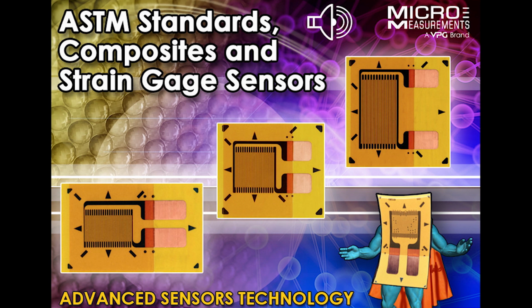It covers the whole area, and if you want to read more about it, I know Bob Watson had a presentation at Micromeasurement about it, where you'll see that if you use an actual shear pattern like an 062 UV, you will not get the whole spectrum of where the strain field is through that specimen. So unless you have a correction factor for these gauges versus reality, you're underestimating what the modulus is in reality. So this is pretty much in a nutshell what the shear would be.